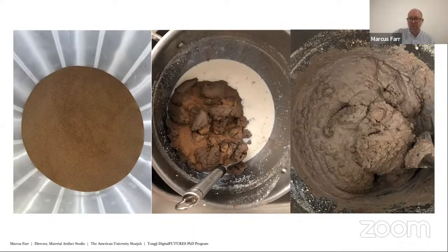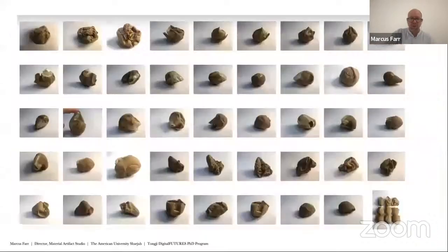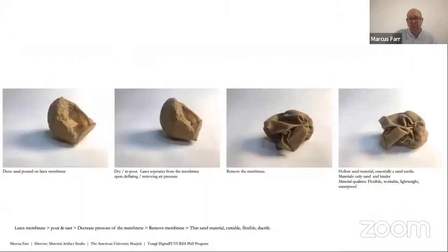We tested it as a formative material for 3D printing. And what was desirable with this material binder as compared to what we did previously with bacteria or sodium was that much higher concentrations of sand compared to additive can be used with this, and it doesn't require a lot of binder to generate a large amount of material. So we tested the workability and the castability of this by pouring it on latex membranes, and then allowing those membranes to change sizes, to get bigger and to get smaller, basically by adding air or removing air.